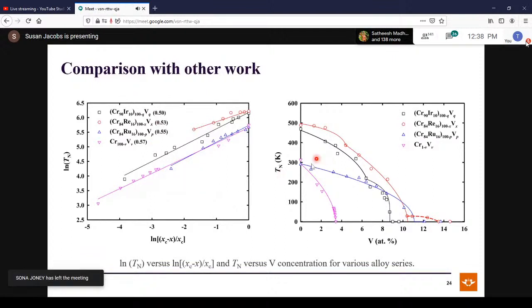Over here, again, we have the Tn as a function of vanadium concentration phase diagram. The red curve is our contribution. Again, there is very close comparison with other alloy systems. Now, in the chrome iridium vanadium alloy system, again, we can see the same thing, a sort of inflection, a sort of change of slope before going quantum critical.